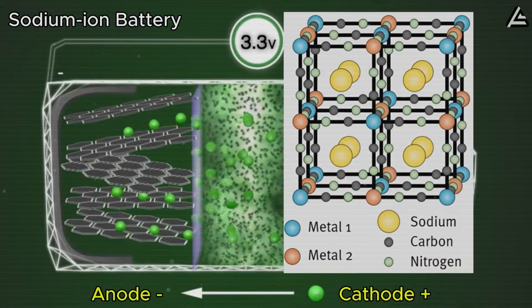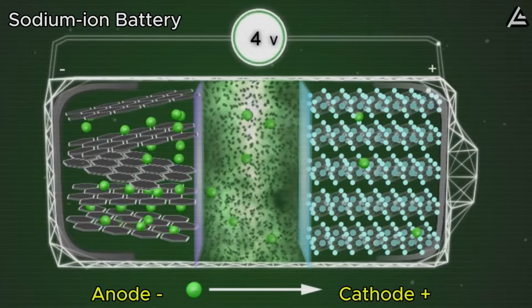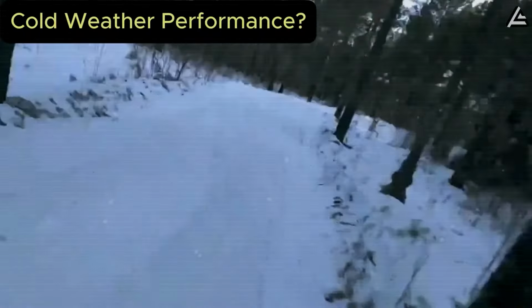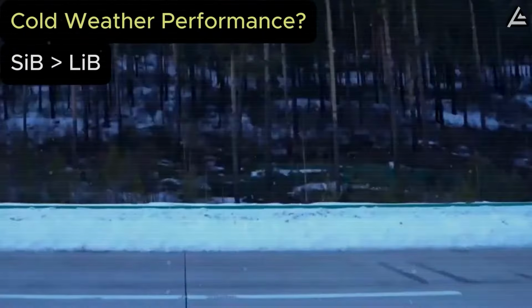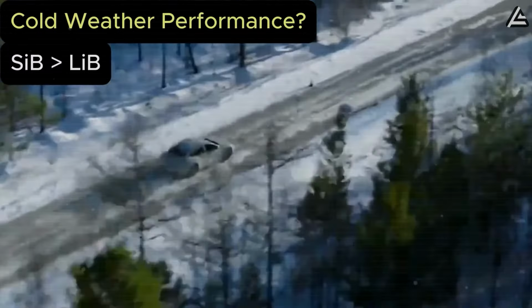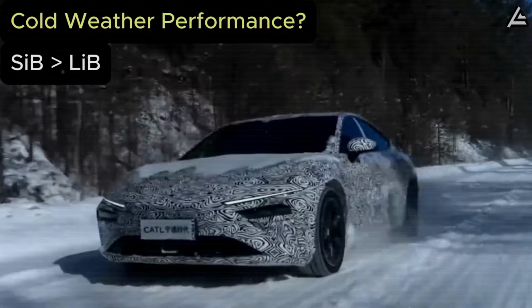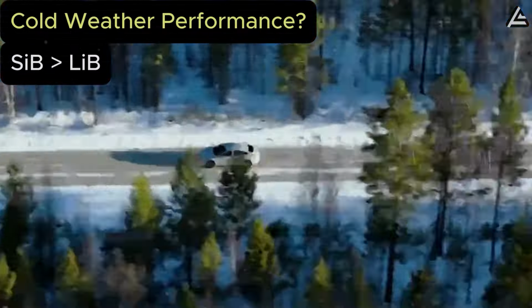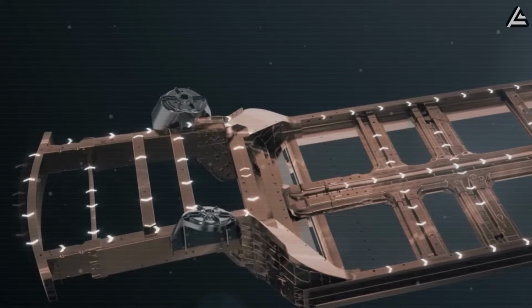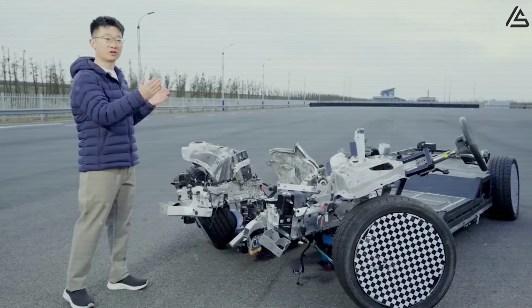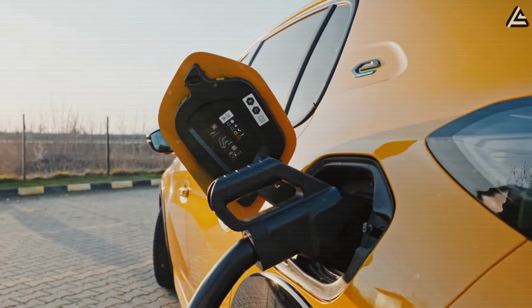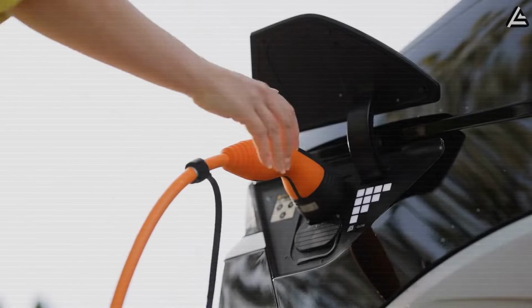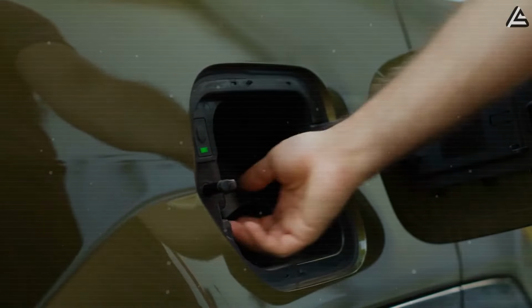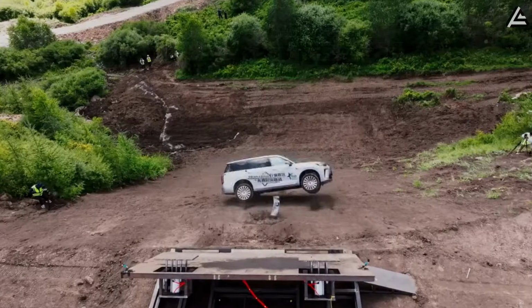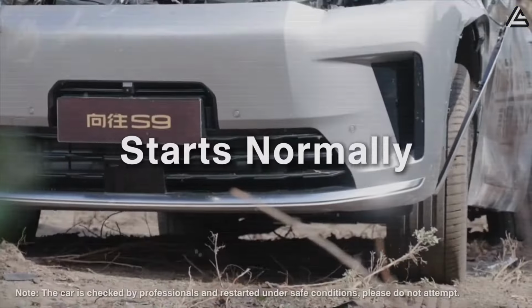Sodium's chemistry is simply less volatile. Its ions carry charge without the same eagerness to react with moisture or oxygen. Add to that its ability to keep 90 to 95% of its capacity even at minus 20 degrees Celsius, and you have a battery that feels like it was designed for Canada rather than California. The trade-off? Sodium ions are bulkier and heavier than lithium, which means slower diffusion and shorter life, roughly 2,000 to 4,000 charge cycles compared to lithium's 5,000 plus. Overcharging can also swell electrodes, which Tesla would need to manage with precision software and cell balancing. Still, in the grand safety hierarchy, sodium ion sits comfortably near the top.